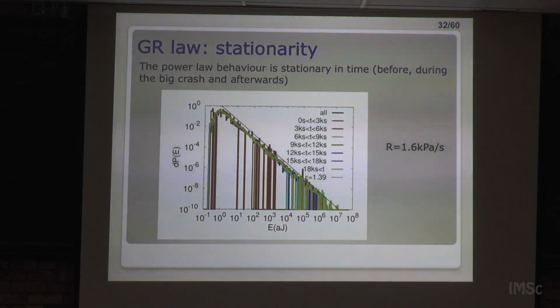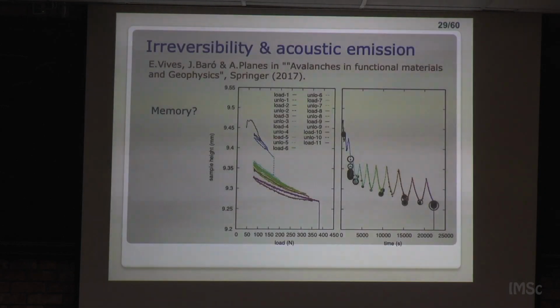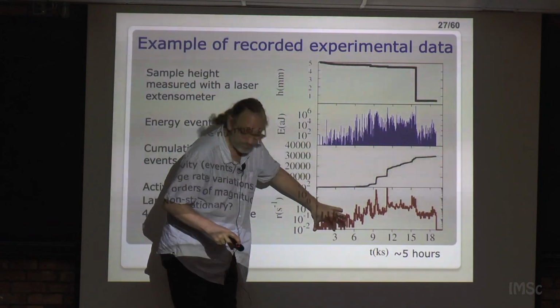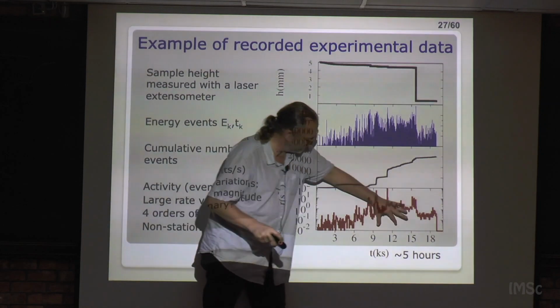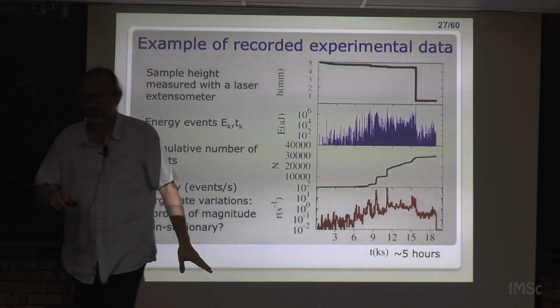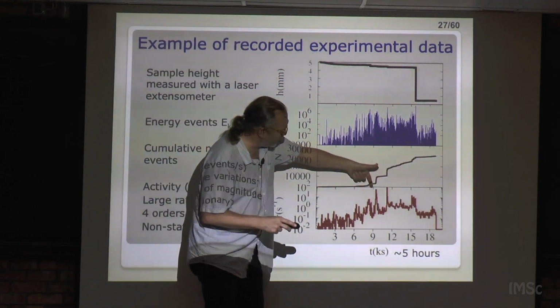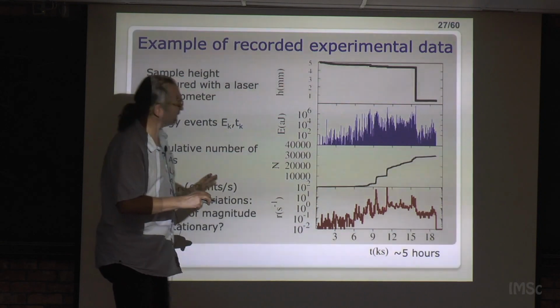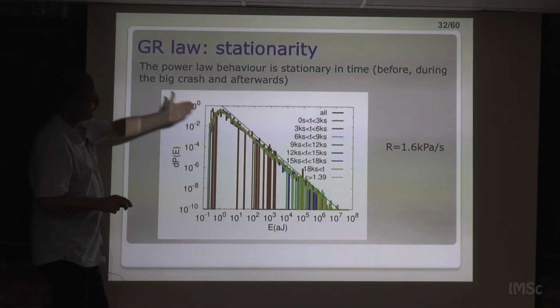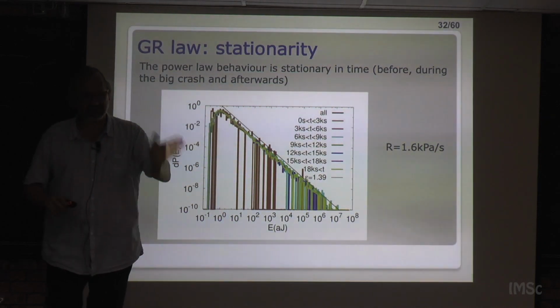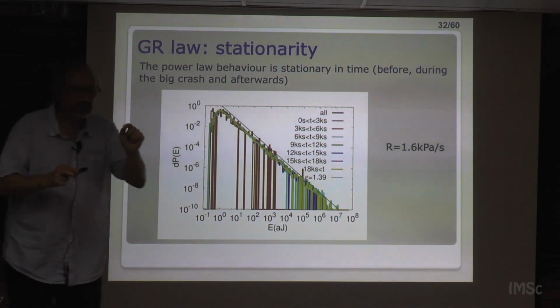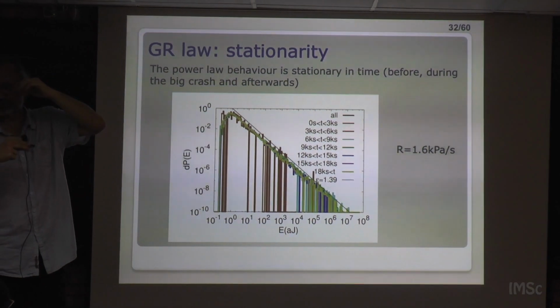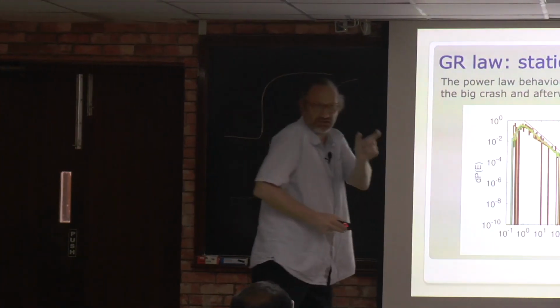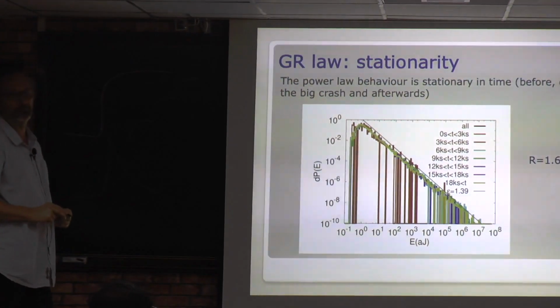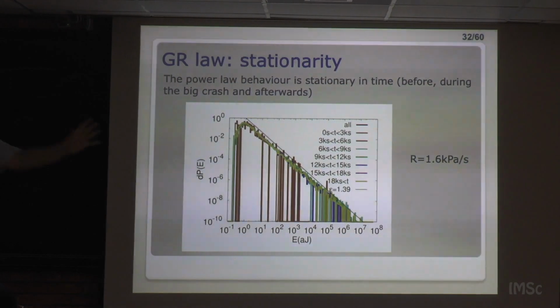Stationarity, this is also important for those of you that are worried about that. Let me go back. If you go here, you take windows of 3,000 seconds, and in each window you evaluate the Gutenberg-Richter exponent. These windows are taken without looking at where the big events are, of course. If you do that, you see these are different windows, all of them with the same slope, stationary. Except maybe in the very beginning, when there is an adaptation of the sample, so the first few seconds are different, but of course we don't have statistics to check that. But if you take reasonably big windows, you get a stationary power law, which is different from many models that have been proposed.